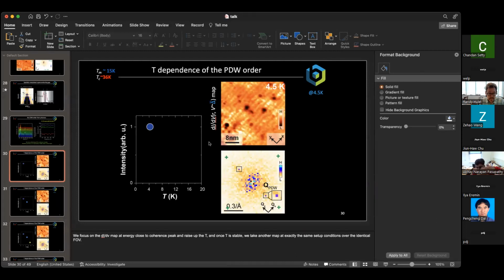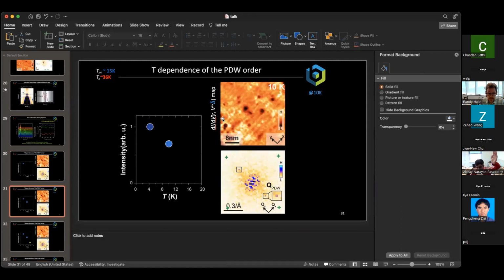If it's just an exchange splitting between the europium and the iron arsenide, then the magnitude of that exchange splitting might depend on the magnetization, which goes down as a function of temperature. Now, what does happen in our data, you can see as you go to 10 Kelvin, and then to 15, which is where the intensity really starts to die out, we start to lose intensity in our feature also. But so far, we have not seen any evidence that this Q is changing. And this would be something that's against this sort of mean field, exchange field idea. Yeah, okay, that's very good. Chetan?